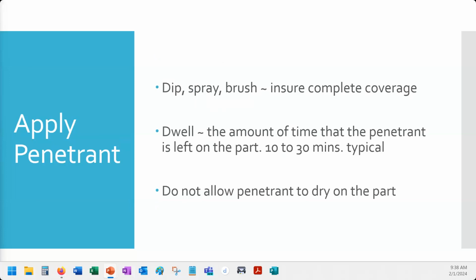We would do penetrant inspections on the turbine cases of the engines we worked on. You could have a crack up to about 2 inches long, as long as it wasn't exceeding a certain value or didn't grow too much between this inspection and the last inspection. Every once in a while, someone wouldn't clean it properly when they were done, and when we rolled around and did the inspection again, the crack would shrink.